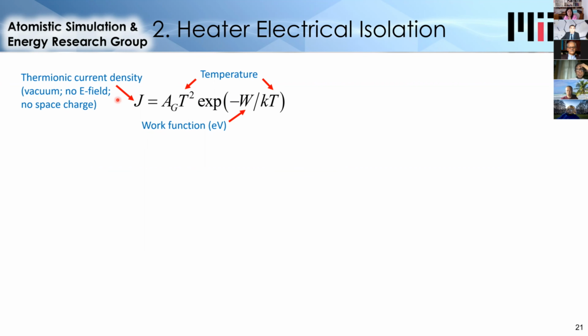So this equation predicts that we would have about 1,000 amps of arcing for the size heater we have, but it relies on assumptions that are not valid in this case. So it assumes that there's a vacuum, whereas we had argon gas. It assumes there's no electric field present, whereas you actually are applying voltage to the heater, so we could actually even get more arcing. But it also neglects the space charge effect.